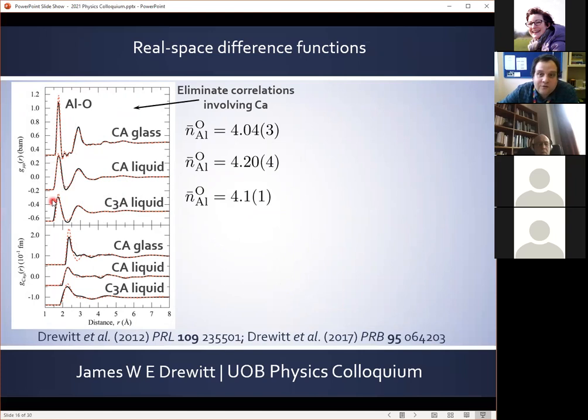So I illustrate this here with the real space pair difference functions. In this first order difference function, the structure factors were subtracted and Fourier transformed. So we've eliminated all those correlations that involve calcium, and we see a very well-defined aluminium oxygen peak here, which we can integrate over and obtain very reliable values for our average aluminium oxygen coordination number. So for calcium aluminate liquid, we find an aluminium oxygen coordination number of 4.2, which changes dramatically on glass formation to around 4 in the glass. And similarly for C3A liquid, we find a coordination number of 4.1.